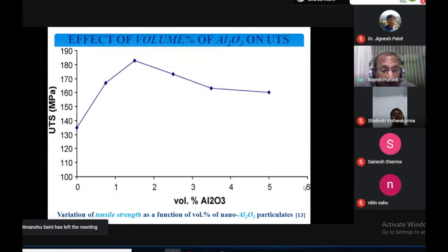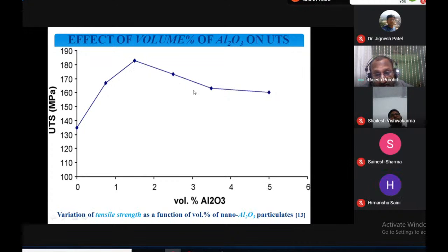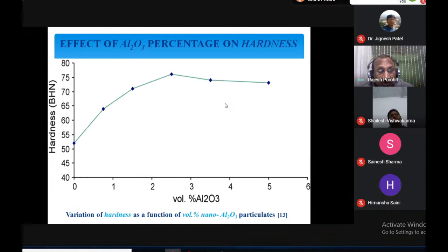This graph shows the variation of ultimate tensile strength with volume percent of nano alumina. Here we see that at about 1.5 volume percent we have the maximum ultimate tensile strength, after which it is decreasing. And this shows the variation of hardness values with the volume percent of nano alumina. Here also we see that at about 2.5 volume percent we get the best hardness, and then it is decreasing.